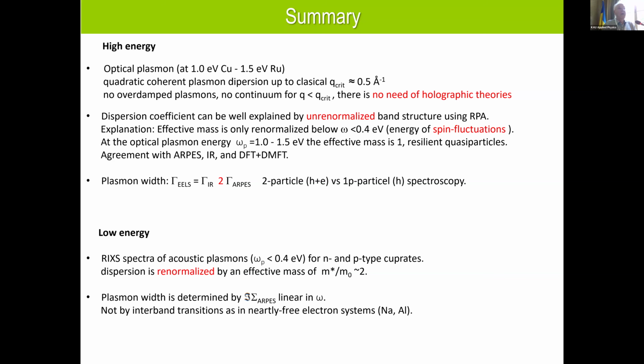And this indicates that the plasmon width in these correlated systems is mainly determined by correlation effects, but in simple metals like sodium or aluminum, the plasmon width is determined by a decay of interband transition, which is backfolded, but these widths are roughly a factor of 20 smaller than those in the correlated system. So thank you for your attention.